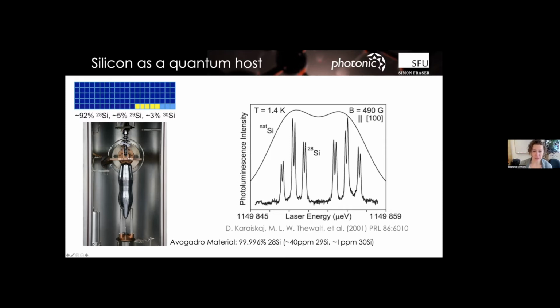right? So in natural silicon, you could take a look at the ensemble line width, all of the different phosphorus spins all contribute to this kind of luminescence, this line width. And if you get rid of the silicon 29, not only does it help with your spin lifetimes by getting rid of the magnetic noise, but it really cleans up your optical spectrum. Now suddenly you can start to see spin states. You can see spin states when you have billions of phosphorus atoms contributing to that signal. These line widths are on the order of 60 megahertz. That's just phenomenal.